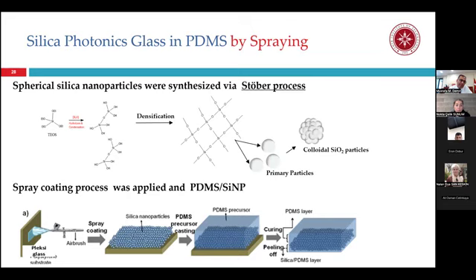We begin with tetraethoxysilane, which undergoes hydrolysis and condensation, then you obtain silica particles, okay? Silica colloids, and they are usually uniform in size if you are careful enough about experimental conditions. So this colloid solution is in water, and it is sprayed on a surface, and we apply a mask of polydimethyl siloxane cast on the surface. Okay, the surface is entirely covered with polydimethyl siloxane. After the curing step, we peeled off the material from the surface. On top, you have polymer. At the bottom, you have photonic crystal, but the photonic crystal structure is frozen in the elastic polymer.